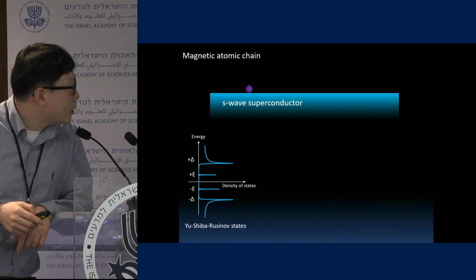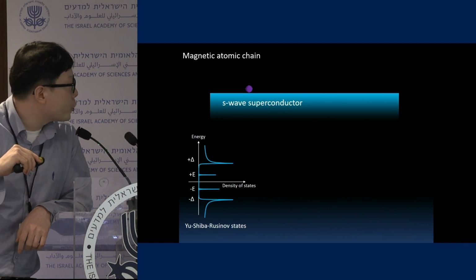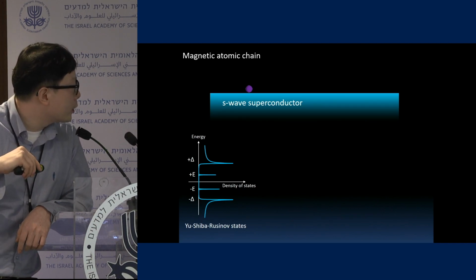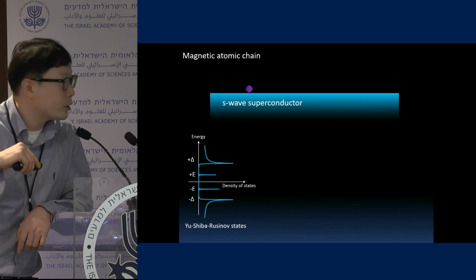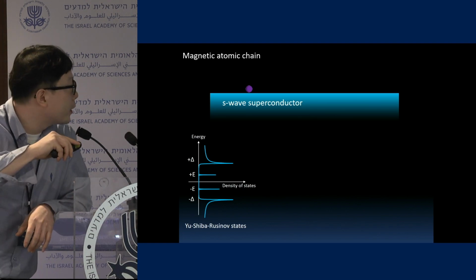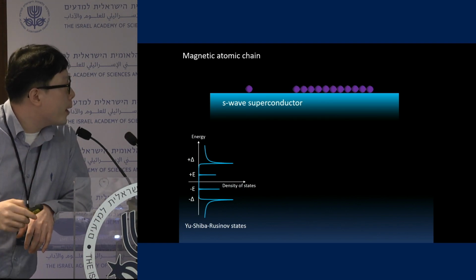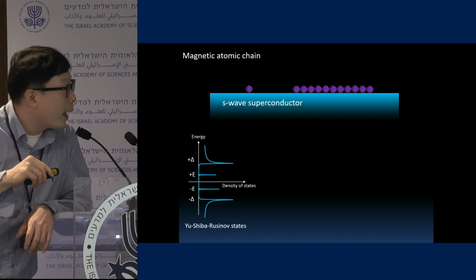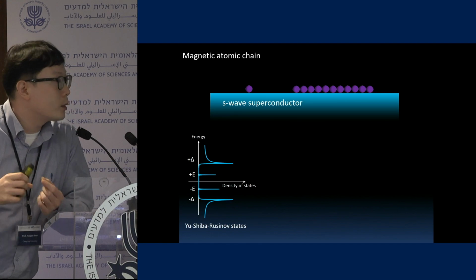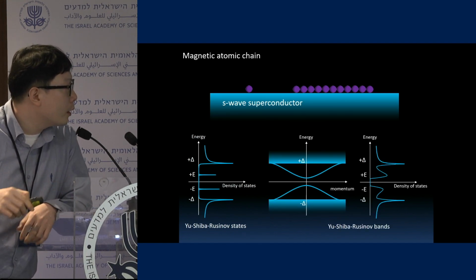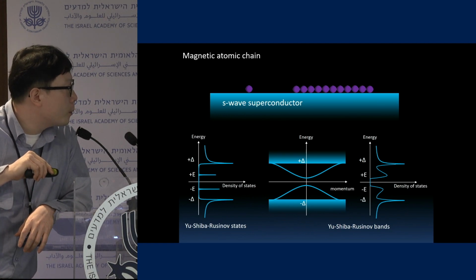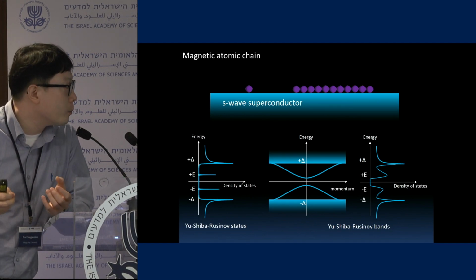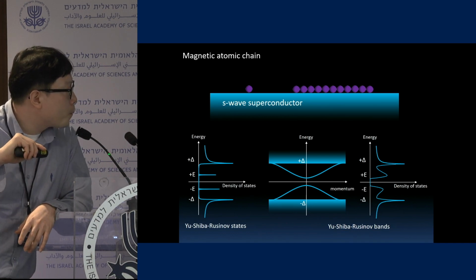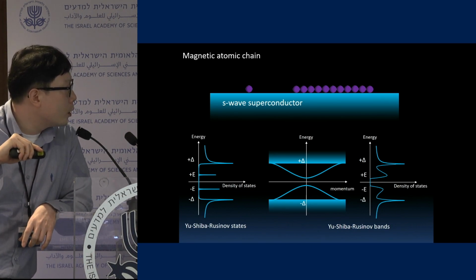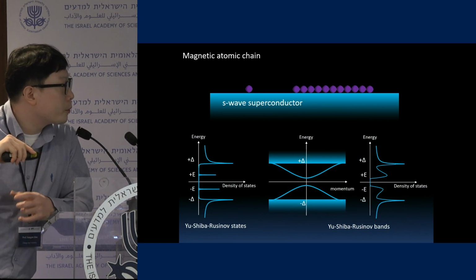Okay, the first part. We know from Yu-Shiba-Rusinov states that once we put a single atom on a superconductor, there should be a bound state inside the superconducting gap. This is very localized nearby here. But once we make a chain out of these magnetic atoms, this localized state will have some dispersion like this. Within the superconductor, the states will make some continuous distribution in momentum space, especially if the bandwidth is small enough such that there is no crossing point between these two. Actually, this is the particle-hole symmetry coming from the superconductivity.